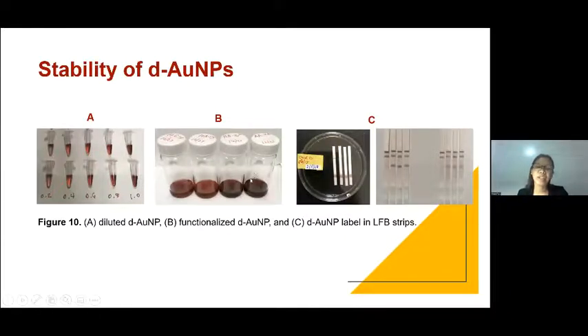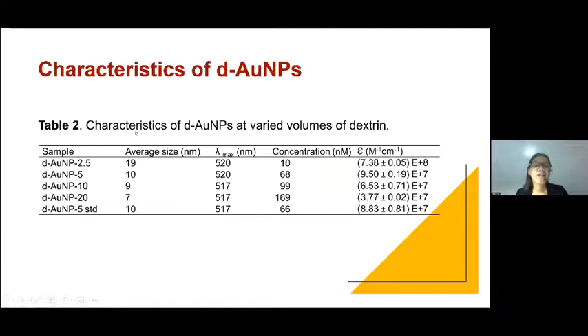Stability of gold nanoparticles can be demonstrated in these figures. In figure A, this is a dilution test for gold nanoparticles, and diluted gold nanoparticles were shown to be stable for more than 6 months, while undiluted as-synthesized gold nanoparticles are stable even after 1 year of storage at 4 degrees Celsius. In figure B, the functionalized gold nanoparticles were found to be stable within 1 month. And the label gold nanoparticle used in LFB stored for 1 month is stable and can still be used. So table 2 gives the summarized characteristics of d-AuNPs at varied volumes of dextrin.